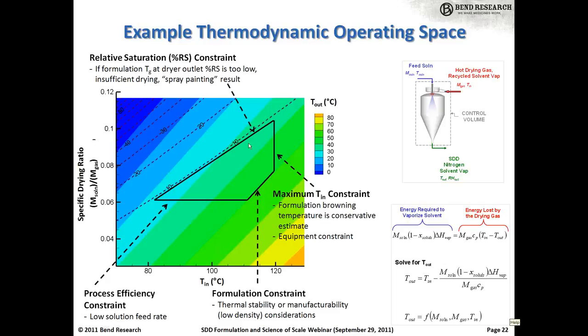So you think of this as, you want to operate above a certain relative solvent saturation, or you lose the driving force for drying. So if you get too wet solvent conditions, you won't actually dry. You'll do what we call spray painting, and the material will stick within the spray dryer, and your yields will drop off. So this constraint can be evaluated offline by looking at the TG of the SDD at different exposure conditions to different relative solvent saturations.